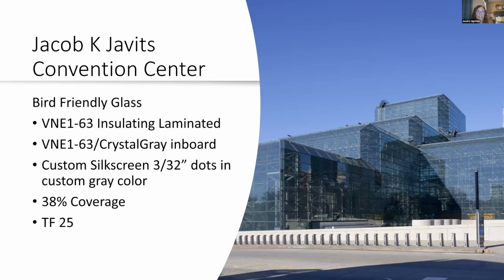This is another example of a project that used bird-friendly glazing. This is located in New York City and is essentially clad in all glass. The Jacob Javits Convention Center is a retrofit design which used a gray dot pattern forming lines. The original building was built in the 1980s, and one of the goals to retrofit was to reduce bird collisions, which was achieved. With the new fritted glass, bird collisions were reduced by over 90%, and this is with the frit on the number 2 surface inside of the outboard glass ply.